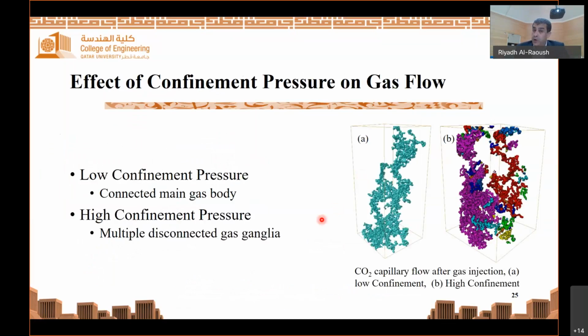This is another study where we use synchrotron microtomography to investigate the impact of pressure on the gas conductivity in sandy sediments. So for the same geometry of the porous media, for the same topology and geometry, you can see that here we can quantify two types of flow regimes. At low pressure here, you can see that the gas phase is highly connected. However, at this high pressure here, you can see that the gas phase gets disconnected into individual or multiple gas blobs.